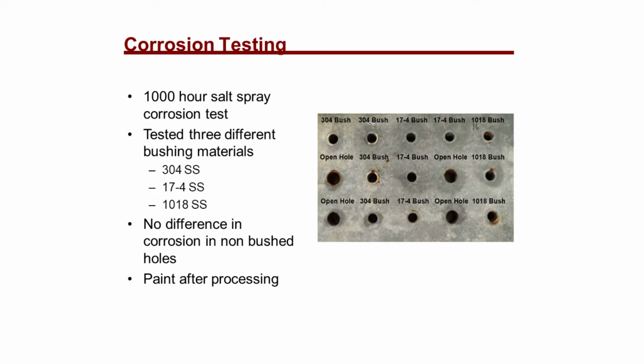We've also recently done some corrosion testing because we are putting steel in steel, so you are going to get some corrosion. We wanted to do some testing to see what kind of problems that would cause. So we used our standard 304 bushing. We also used a 17-4 bushing, which is our alternative bushing for stronger steels. And then we also put a 1018 bush in there. The reason we did that is because we're doing work now in some structural steels for the pulp and paper industry, and they use a lot of 1018. So we wanted to see what the corrosion would look like with that.